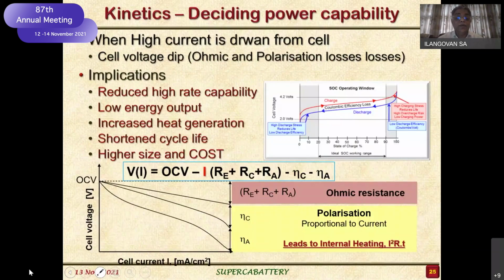Technically, or electrochemically, when I look at it, the open circuit voltage is reduced by I times. If I increase the current, automatically this host of resistances, like charge transfer resistance and electrolyte resistance, will pull down the voltage. Not only that, it will also generate heat, which is responsible for bringing down the efficiency and cycle life of the battery, because of hot spots, separator functioning, and dendrite growth. All these mechanisms are setting in.